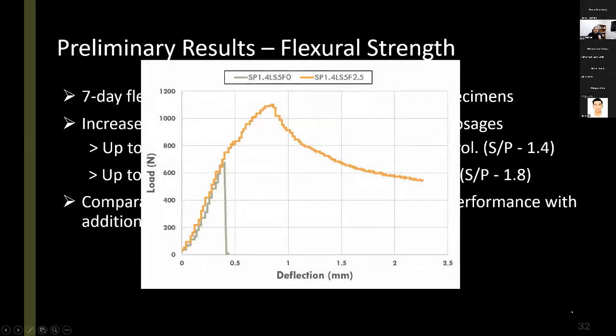And we will do more, deeper measurements and investigation into the flexural properties and the ductility of these materials. But we already are seeing some early signs of improvement in ductility. So here you can see some rough measurements we did in terms of the deformations of layers.